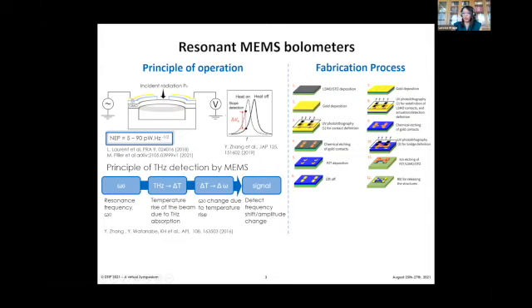So we have a fabrication process that's simpler to implement. And by using this, our main objective is to achieve the epitaxial PZT through a room temperature process to allow this lift-off. So we're really focusing on the 6th step of the fabrication process here. And this structure has been proposed by different groups, but not yet with oxides. That's why we're using the LSMO as the basis here.